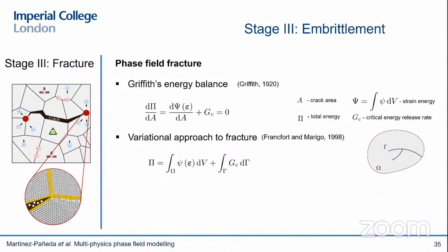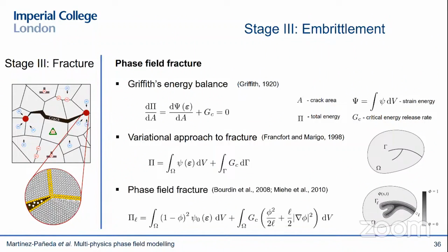However, the challenge here is that you don't really know where your crack surface lies, so it's a bit complicated to solve this computation. And this is where the phase field comes to our rescue, because we can use the phase field as a marker. It will go from 0 outside of the crack, in intact material points, to 1 inside of the fully cracked material points, and it will degrade the stiffness of the solid accordingly. And you can see here that it's kind of a non-local damage model because it has a gradient, and therefore a length scale, which means that your results will be mesh insensitive, so mesh independent.